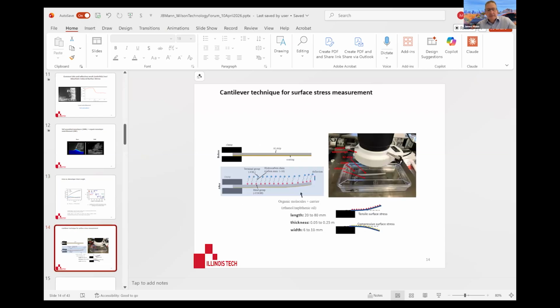And recently we've actually explored these surface stress effects in a very interesting macro scale experiment where we take a simple cantilevered beam strip of aluminum, and then we expose one side of the beam, in this case with a hydrocarbon, and we can actually measure the deflection.